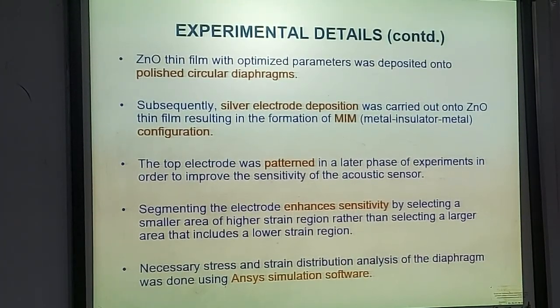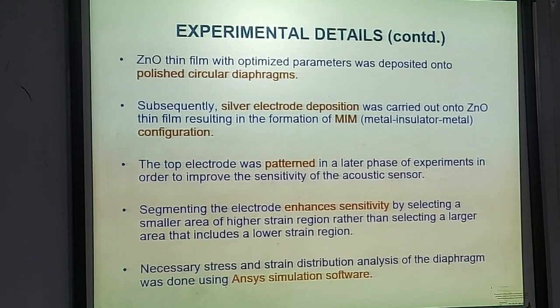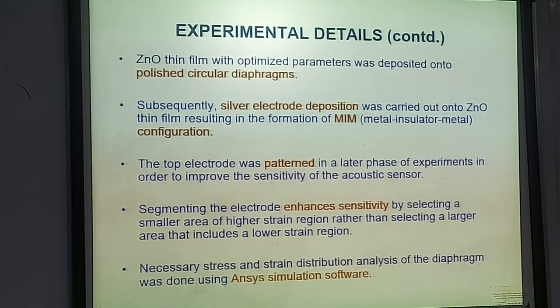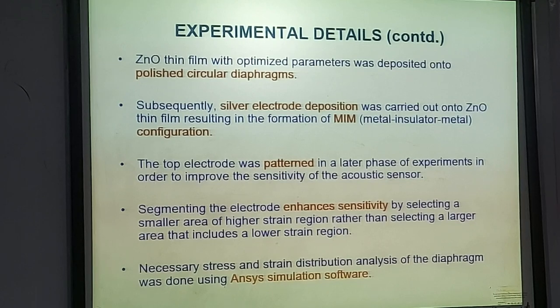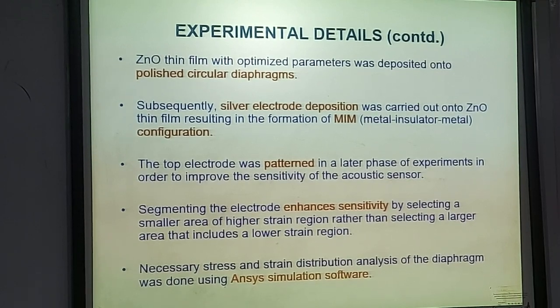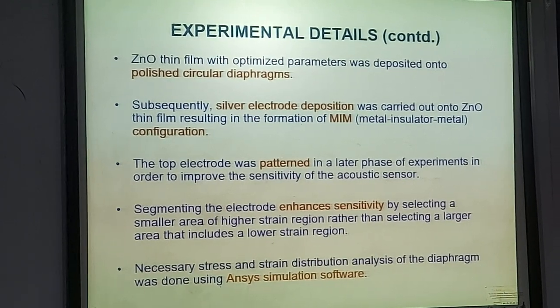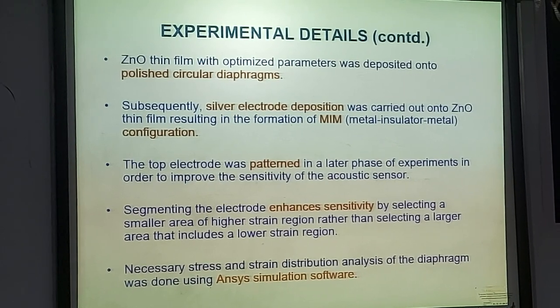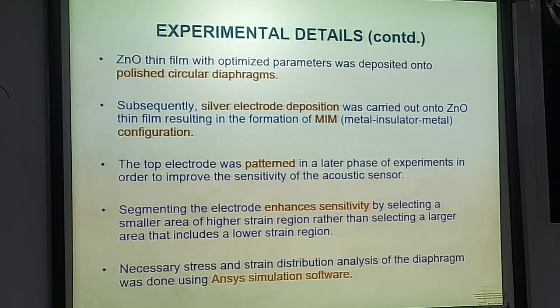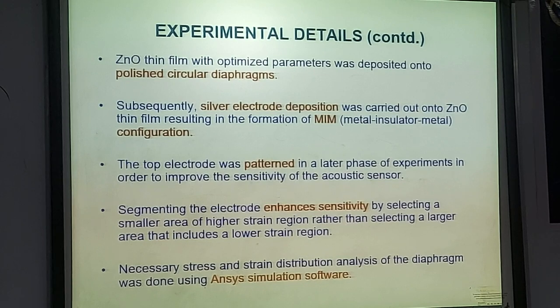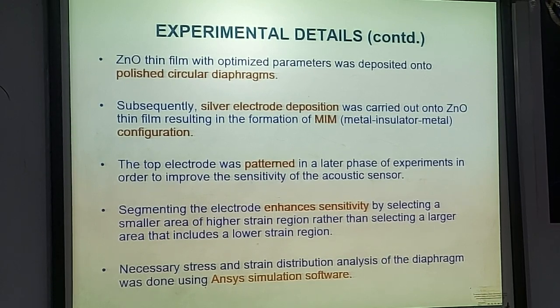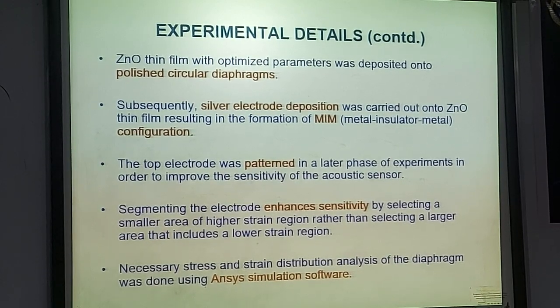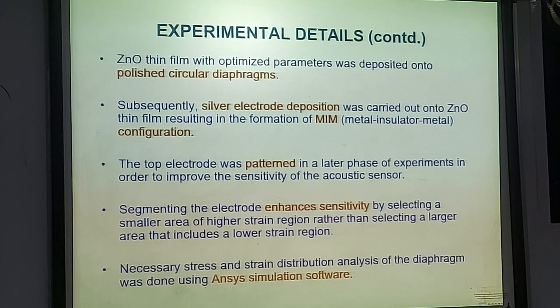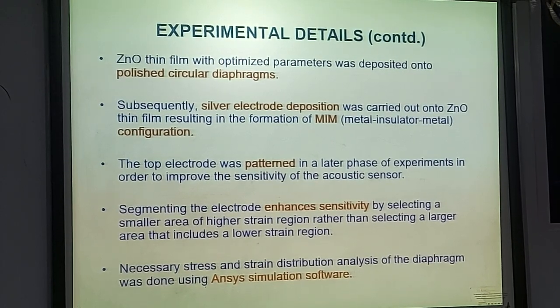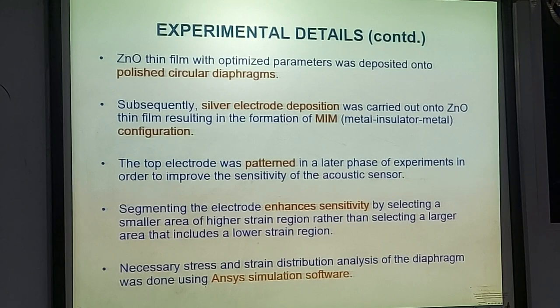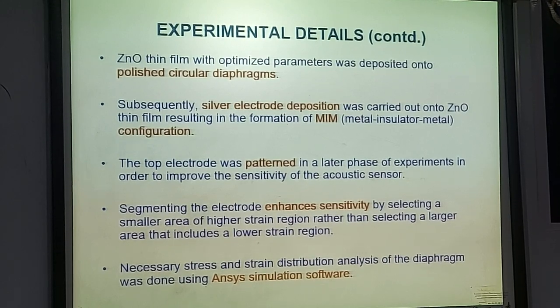Then this zinc oxide thin film with optimized parameters was deposited onto circular diaphragms. Subsequently, silver electrode deposition was carried out onto the zinc oxide thin film, resulting in the MIM structure, metal insulator metal configuration. The top electrode was patterned in a later phase of the experiment in order to improve the sensitivity of the acoustic sensor. And we found that segmenting the electrode enhances sensitivity, and the necessary stress and strain distribution analysis on the diaphragm was done using a simulation software.